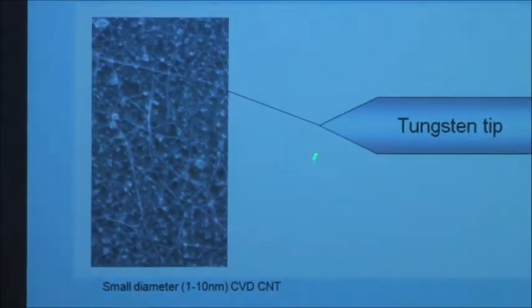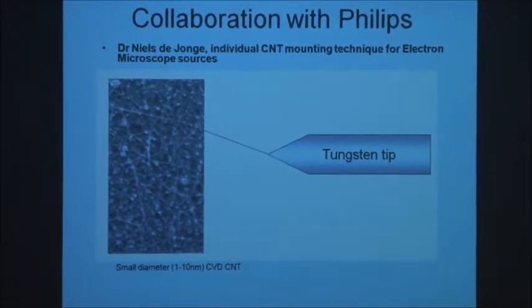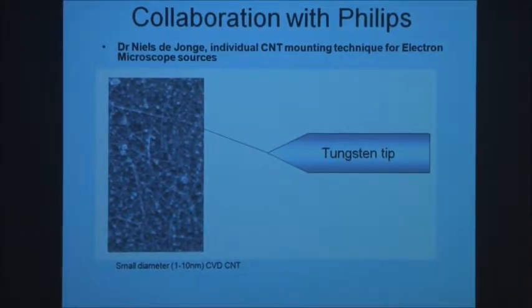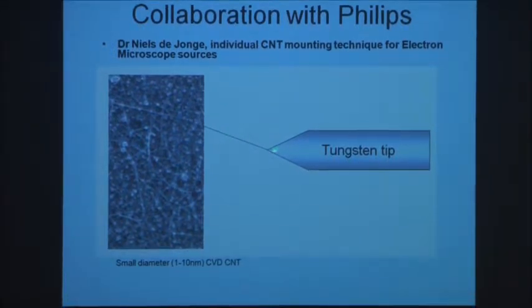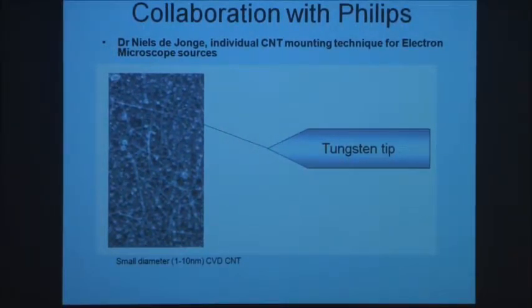So what we tried to do was produce carbon nanotubes as electron emitters for a TEM and SEM. We did this in collaboration with Philips a few years ago. We started off by taking a typical field emitting source for a microscope, which is actually a tungsten tip. Normally they would use a tungsten tip, and then you bias and the electrons would emit from here. But we thought if you could put a carbon nanotube on top of the tungsten tip, then you get an enhancement of the enhancement, if you want. The enhancement tends to be related to the diameter of the tip and the length of the tube. So we thought, okay, the first thing we'll do is start off with spaghetti-type nanotubes.